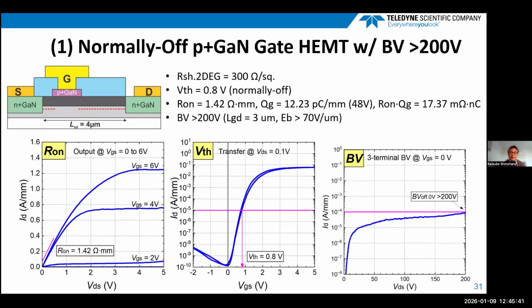So in order to make the normally off super heterojunction devices, we first demonstrated the normally off p-GaN gate devices using our conventional AlGaN HEMT structures. And here I show the device cross section having the p-plus GaN gate, which was regrown by MBE. The sheet resistance of the AlGaN/GaN is 300 ohm per square. And this device shows a threshold voltage of 0.8 volt, and a low R-on of 1.42 and QG of 12.23, resulting in R-on QG of 17.37 milliohm nanocoulomb. The breakdown voltage of this device is more than 200 volt.